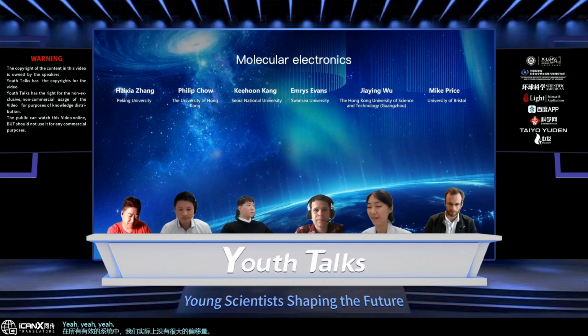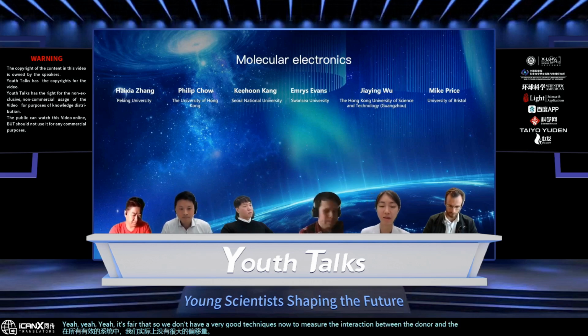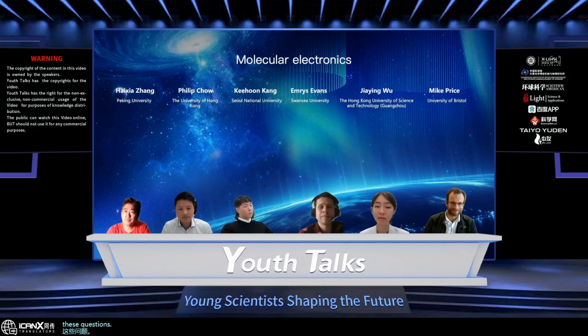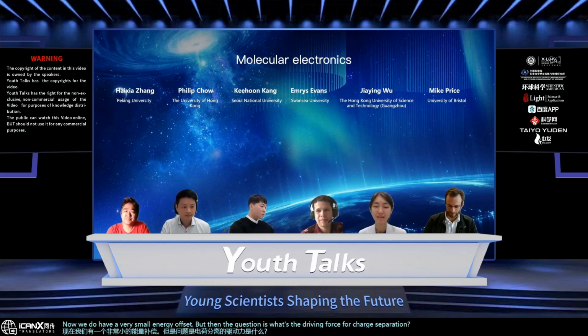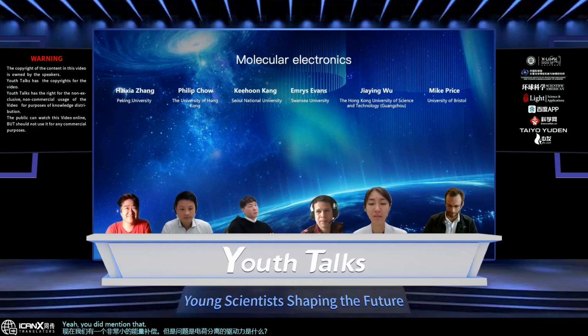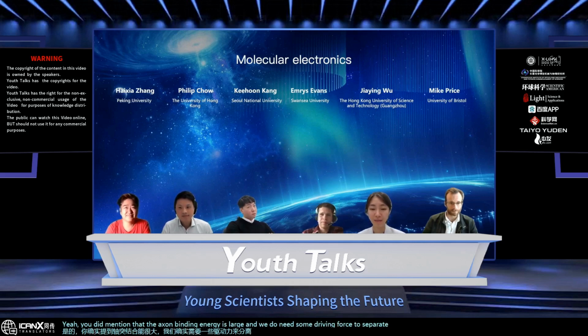Yeah, indeed. It's fair that we don't have very good techniques now to measure the interaction between the donor and acceptor. Just to follow up on these questions: yes, now we do have a very small energy offset, but then the question is what's the driving force for charge separation? You did mention that the exciton binding energy is large, and we do need some driving force to separate them. But what is it now? If the offset is below 100 milli-electron volts, that's already smaller than the binding energy. Do you have any thoughts on that?